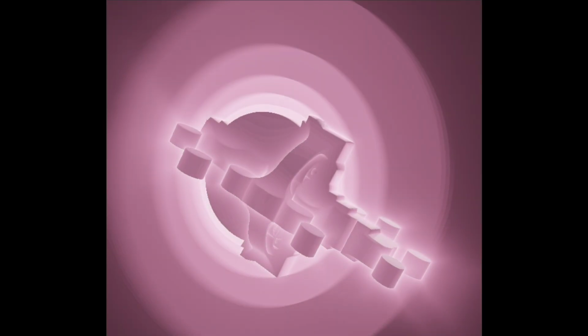Okay, so insulators, superconductors. What about magnetism? Flat bands should help that too, right? Less kinetic energy means exchange interactions matter more. Exactly. The reduced kinetic energy boosts the tendency for electron spins to align. We see this in twisted magnetic insulators, like chromium triiodide. Twisting two layers creates a Moiré pattern in the magnetic coupling between layers, leading to coexisting ferromagnetic and antiferromagnetic domains on the nanoscale. So you can pattern magnetism with a twist.